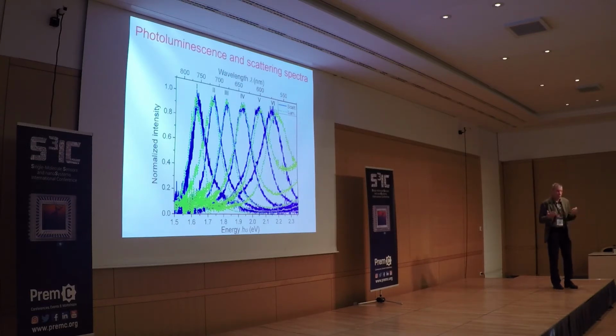And you see that the spectrum is very similar to the scattering spectrum. Why? Well, there's no mystery. It's just photoluminescence is also plasmon enhanced, just as the scattering is plasmon enhanced. So the same enhancement factor influences both spectra. And you see that, of course, the 2 spectra are not exactly identical. There is in particular a little shift here. But roughly, this allows you from the scattering spectra or the luminescence spectra to get the information about the plasmon. And this is, of course, very convenient for us because all our setups are geared for fluorescence or luminescence. So we just need to replace our molecules by gold nanoparticles, and we can just do the same experiments. Whereas the white light scattering requires a different source and different adjustments and different objectives.